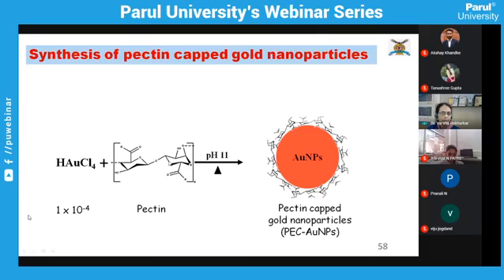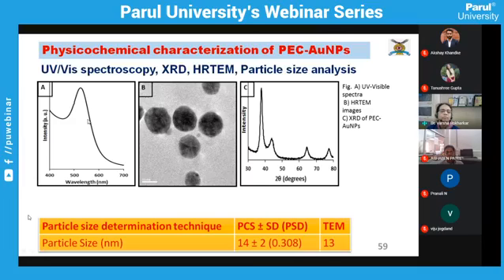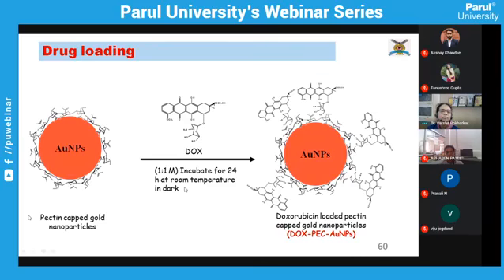The synthesis is similar to what we have seen in the earlier case. The gold salt is reduced using the polysaccharide pectin, which contains essentially alpha-1,4 polygalacturonic acid residues and which is responsible for the reduction of the gold salt, leading to the formation of pectin capped gold nanoparticles. We did the characterization using surface plasmon, HRTEM and XRD studies, and the particles were around 14 nanometer in size. The drug loading is the same. We did it by the incubation method, and the drug, doxorubicin hydrochloride, is anchored through electrostatic charges onto the surface of the gold nanoparticle.